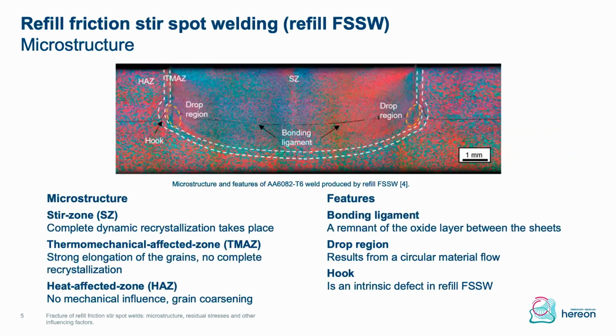Refill friction stir spot welding results in a typical microstructure, as you see here, where we have the stir zone in the middle of the spot weld, where we have complete dynamic recrystallization. Next to the stir zone, there comes the thermomechanically affected zone, where we have strongly elongated grains, but no complete recrystallization. And next to the thermomechanically affected zone, we have the heat affected zone, where we don't have any mechanical influence anymore, but still thermal influences, which result in grain coarsening.